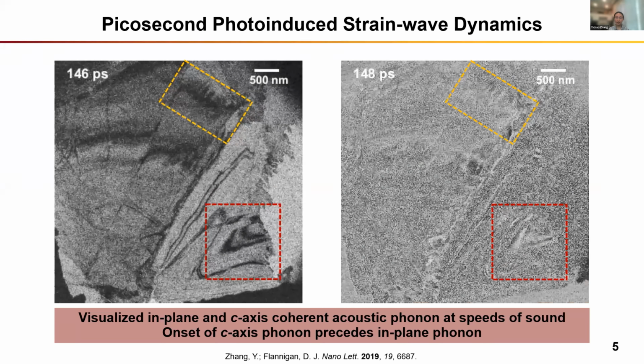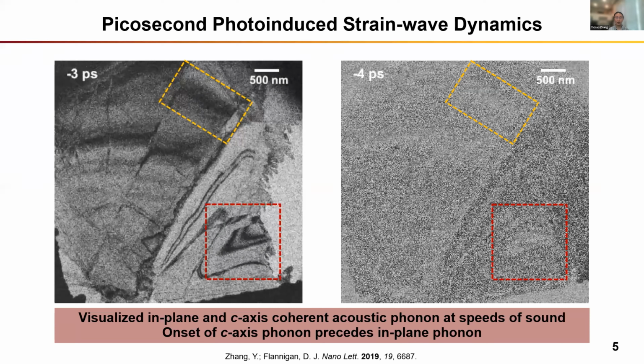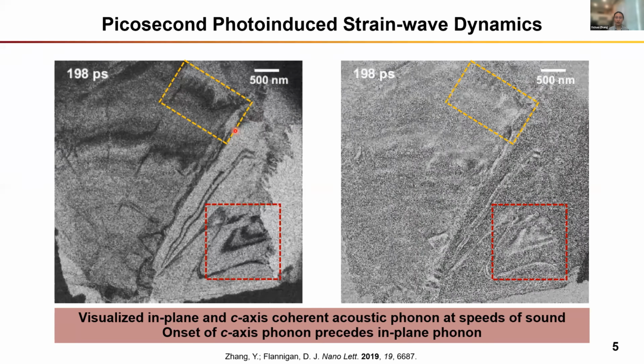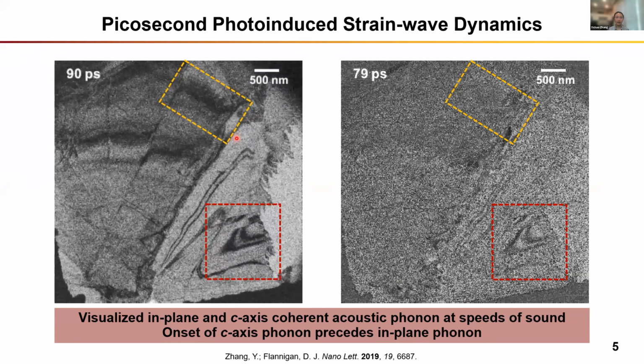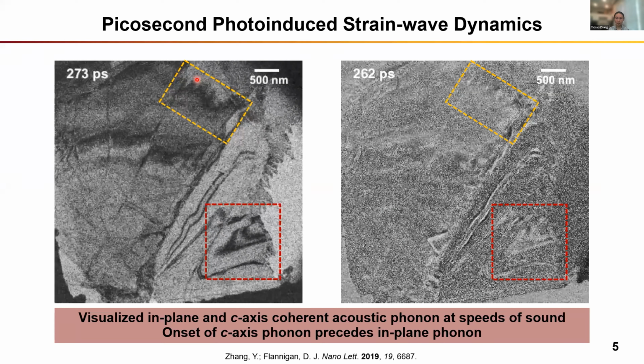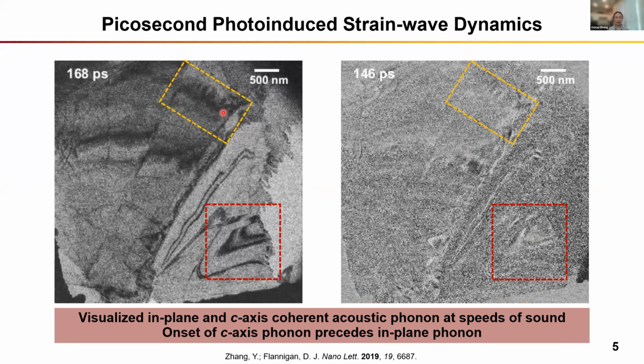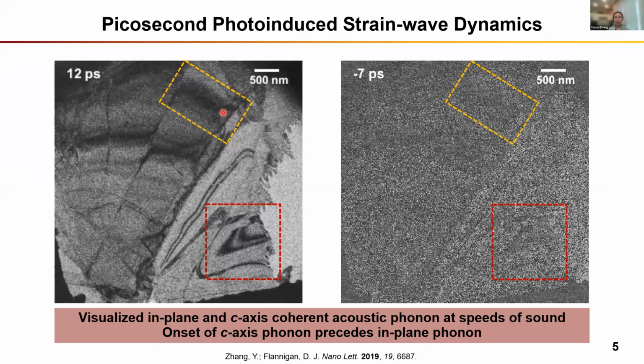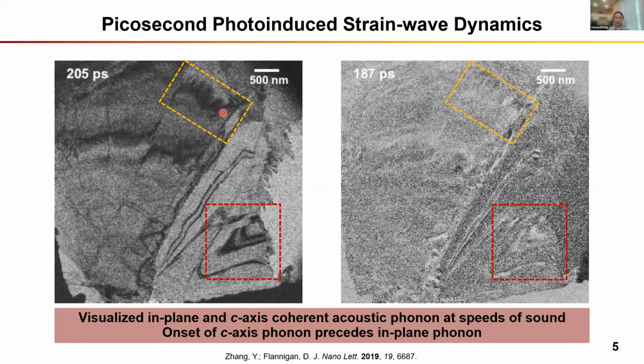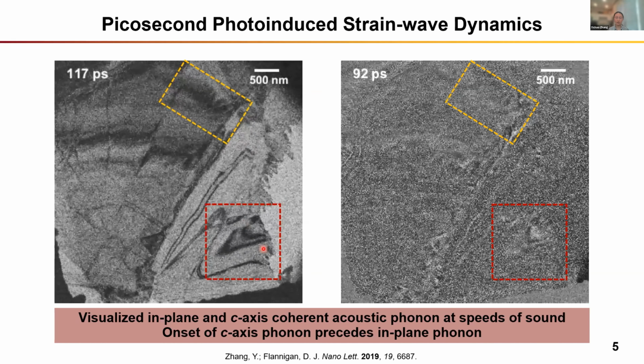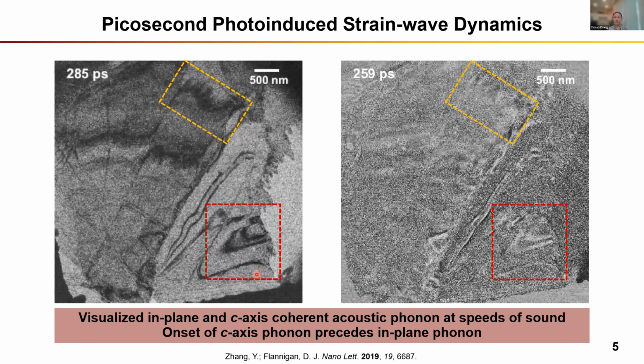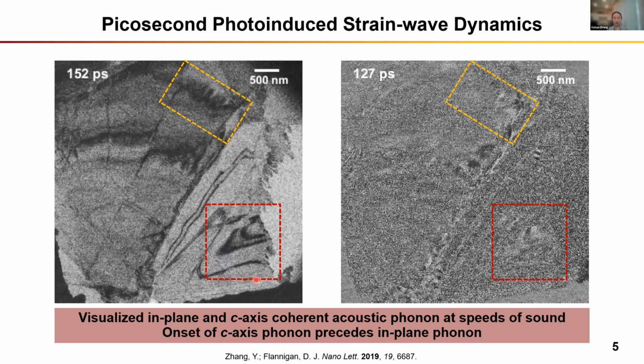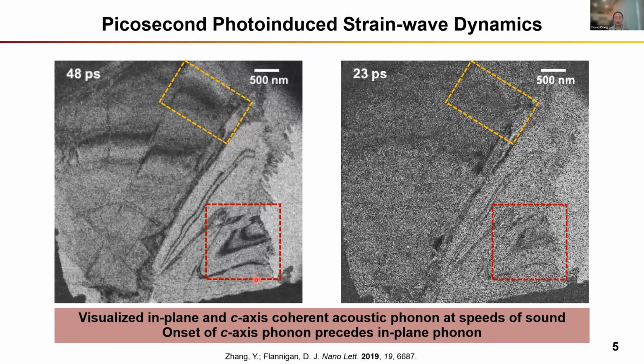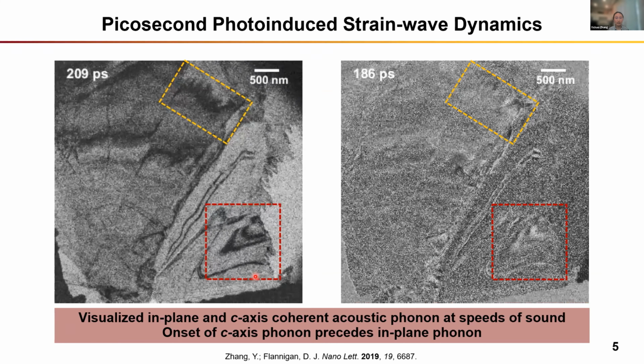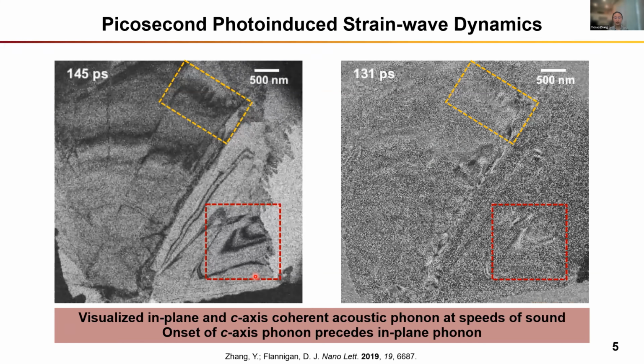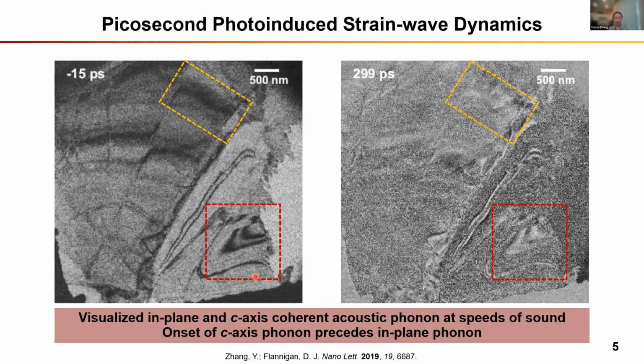In this experiment, we use visible light to excite the crystal. There are two major regions of interest, or ROIs, highlighted by the colored boxes here. In this yellow box, we can see waves generated at this crystal-crystal interface, and they propagate inward along the bend contours. These are the coherent acoustic phonons traveling in the in-plane direction, and we can extract an in-plane speed of sound velocity here. In the red region, however, we can see this V-shaped bend contour that's oscillating locally. This is the c-axis coherent acoustic phonon bouncing between the top and the bottom of the crystal. Due to the projection nature of the TEM and the tilted nature of this region, we can visualize the c-axis dynamics as the oscillation signals here.